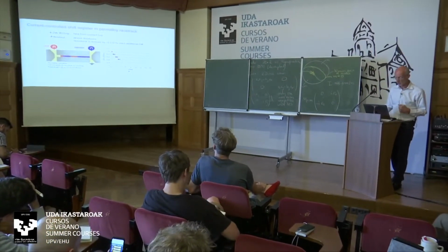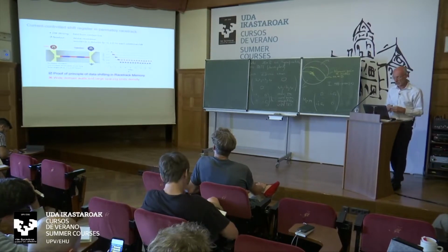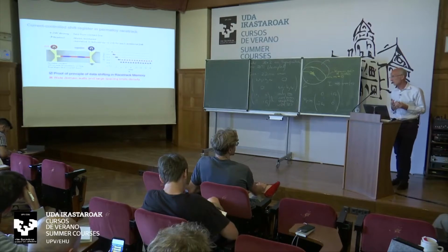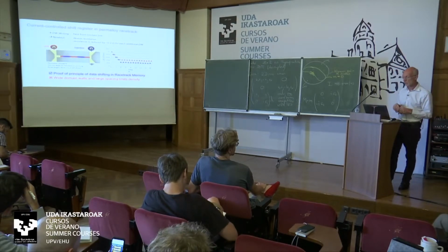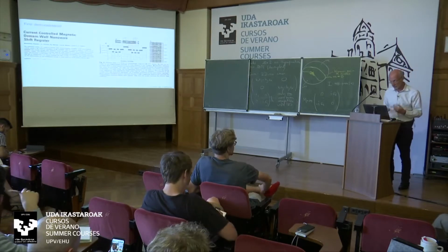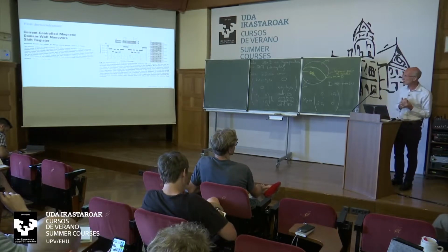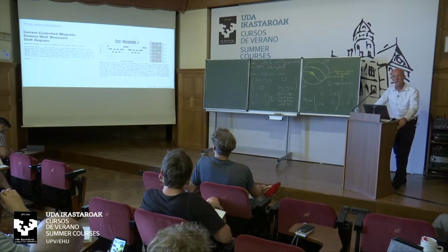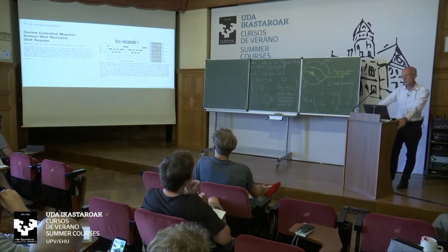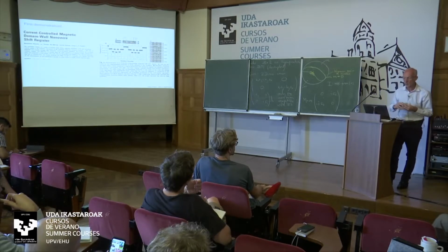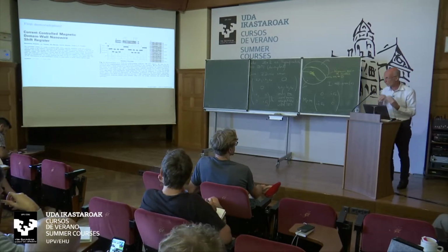Well, this just shows the same thing again. It's a very neat effect. And the problem here, though, is these soft magnetic materials, which typically have these vortex walls. The domain walls are too wide to be useful, which limits the density. Nevertheless, we published this in Science 10 years ago as the first demonstration of the notion of creating and shifting a series of domain walls in this way. And so this, if you like, is the first domain wall nanowire shift register in this proof of principle.